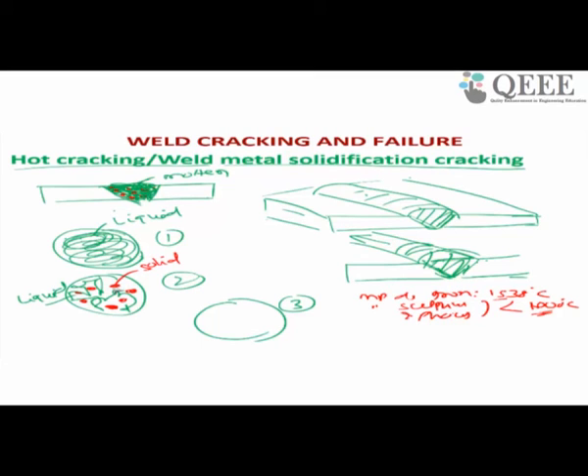Then what will happen during solidification? The material which has the high melting point will solidify first. Since iron has a high melting point, iron will solidify fast. Since the melting points of sulfur and phosphorus are low, it will push the sulfur and phosphorus away from this region. So the solid crystal is rich in iron, and the liquid metal is rich in sulfur and phosphorus.